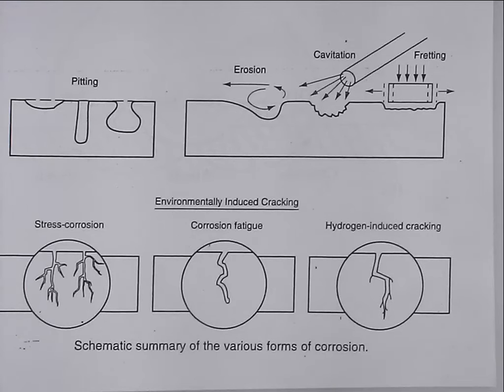In hydrogen-induced cracking, the stress is still at right angles to the crack growth. So the reason why hydrogen embrittlement, or hydrogen-induced cracking as it's sometimes called, is in the same batch is because they all have this one thing in common. The crack grows at right angles to the loading direction. But otherwise, the first two are anodic corrosion processes, and the third one isn't.